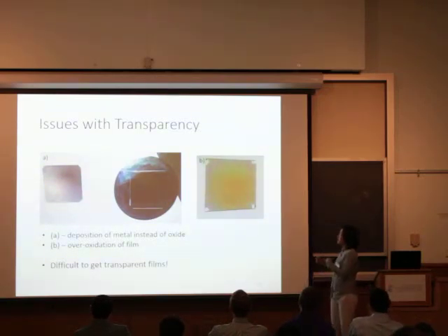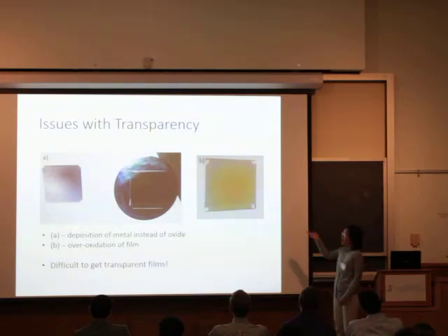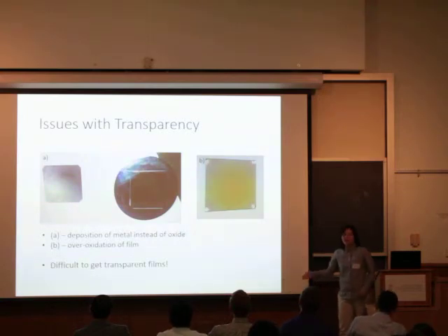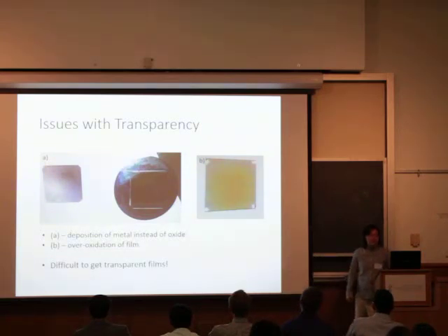The second one shows over-oxidation of the film, resulting in this dark brown-gray color. This was due to overexposure to oxygen, ironically the reverse of the previous problem. We attempted to correct for this by carefully controlling when we exposed the film to oxygen.